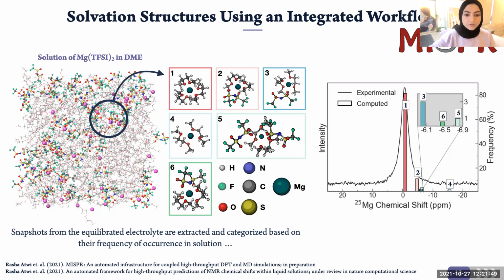From these configurations, we computed their NMR chemical shifts, and we directly correlated them to the experimental NMR peak, instead of the conventional approach that relies on developing these configurations using trial and error methods that not only can lead to errors, but also are time consuming, and might lead to missing certain important speciation that's not possible to predict using human or chemical intuition. And also in the conventional approach, usually they try to match one structure to the peak center only, whereas in such dynamic solutions, it's possible to have multiple structures in the solution.